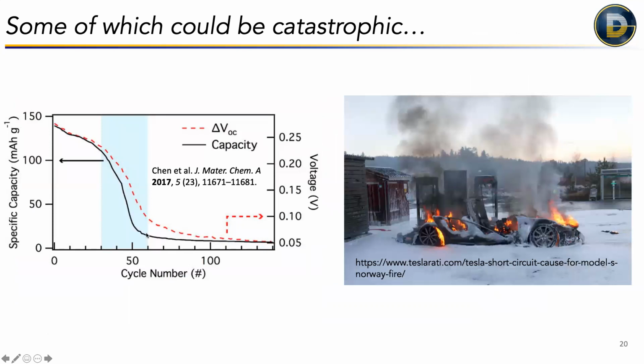And if one of those dendrites happens to penetrate across that 10 micron thick separator, very, very thin, then you could get a short circuit and have some really big safety concerns. To be clear, this is not a dendrite caused fire. There was a short circuit in the charging system, but the effect could be similar if you have a flammable liquid electrolyte around. And the electrolytes that are currently used in lithium-ion batteries are these organic solvents that are very, very flammable. So if you do get a fire, it's going to be very problematic.